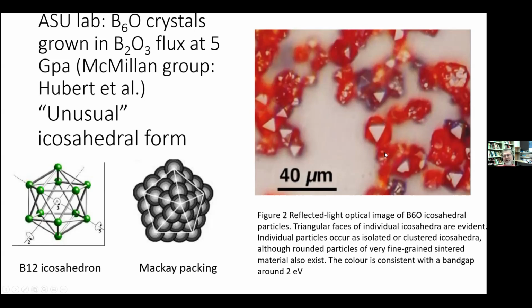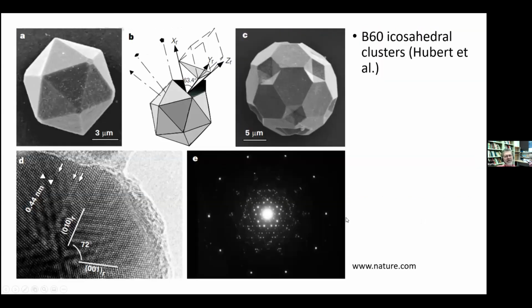And what happened was that the crystals, unexpectedly to us, formed icosahedra, and Mike O'Keeffe was fortunately on the project and just looked at it and said, oh, it's McKay packing. And this is what McKay packing is. It's packing of spheres into an icosahedron, but in this case, it's actually packing of icosahedra into an icosahedron. Here's some more pictures. This is a SEM picture of one of the nice icosahedral particles. What it really is, B6O is rhombohedral, and it has a rhombohedral angle of 63 degrees. So it's quite close to the interior angle of an icosahedron, and therefore they can twin. It's actually a compound of 20 twins that form an icosahedron.